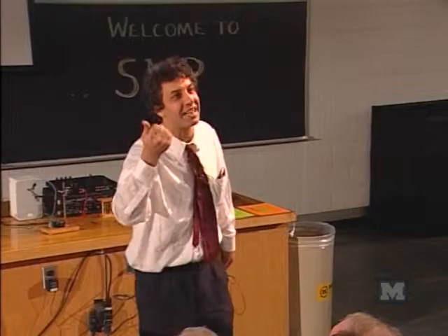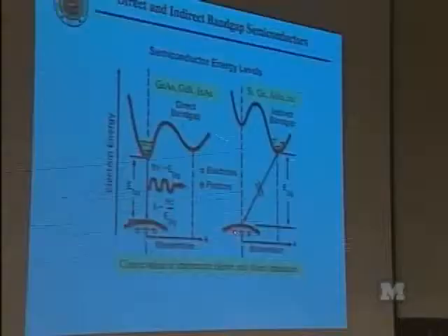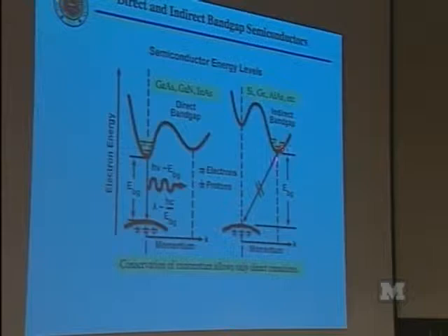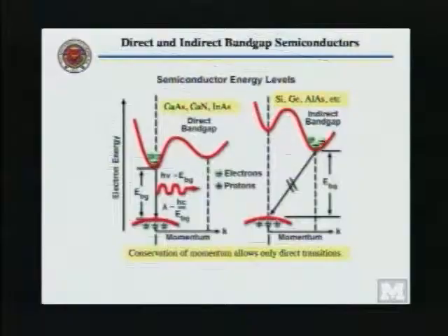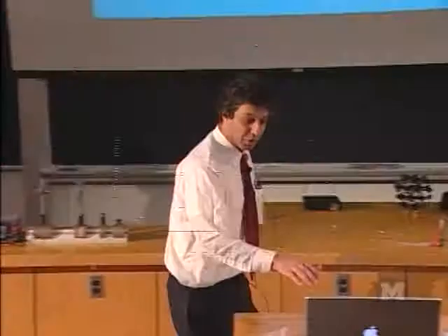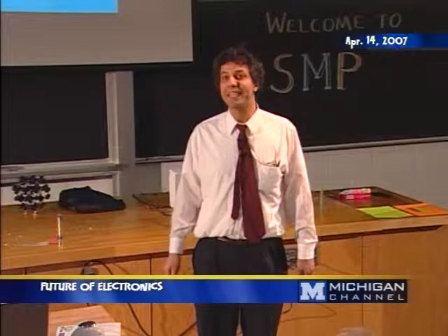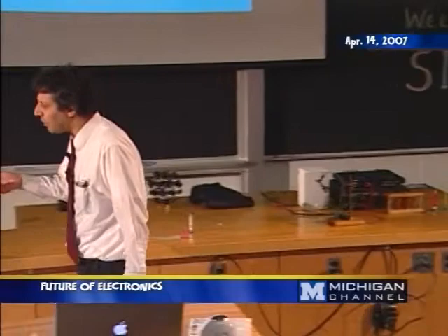In many other semiconductors, the band calculations or measurements tell us that the alignment is such that where the electrons end up is not in momentum space at the same place as the holes. And in these situations, unfortunately, conservation of momentum does not allow that transition, so you would not get light out of this. So in silicon, the diode, which one can make, optically speaking, cannot be used to get light. But in direct band gap semiconductors, you can. And a diode is a very simple device.